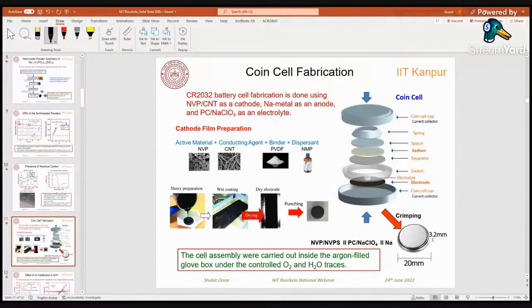So we fabricated a coin cell using this developed NVPS material, and you can see the morphology of NVP, and we have used CNT as an additional conducting agent. We use PVDF as a binder, which is dissolved in NMP solvent.